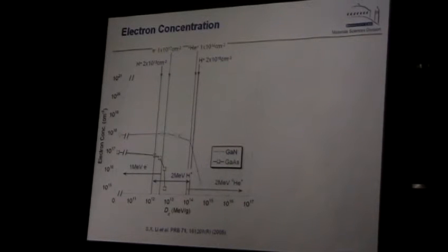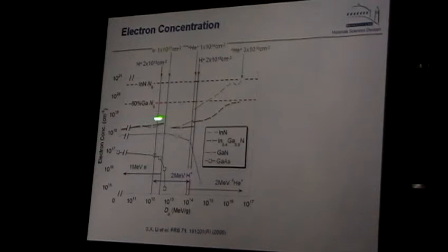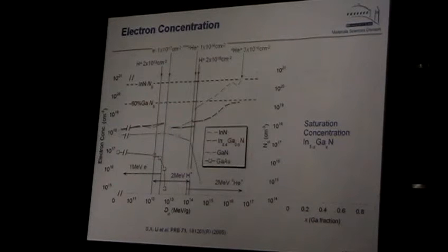And in fact, when we did irradiation, these are experimental results, we see that the concentration of electrons in the case of gallium arsenide and gallium nitride goes down, as expected, because the Fermi energy moves into the band gap. However, when we do the same studies on material with high indium content, where the Fermi energy is in the conduction band, the concentration goes up and saturates at a certain level. And we know how it behaves as a function of gallium fraction, so basically as a function of composition.